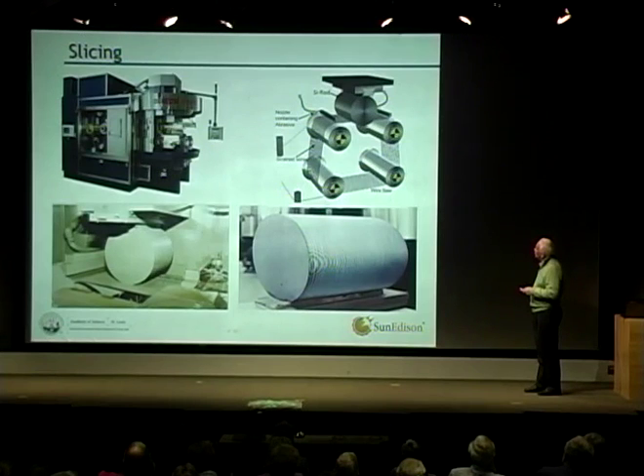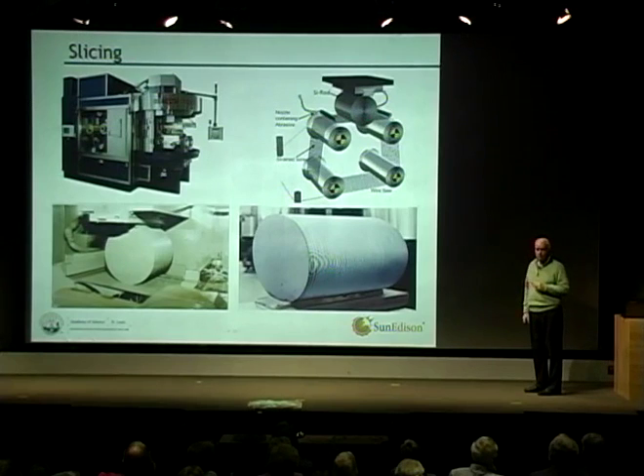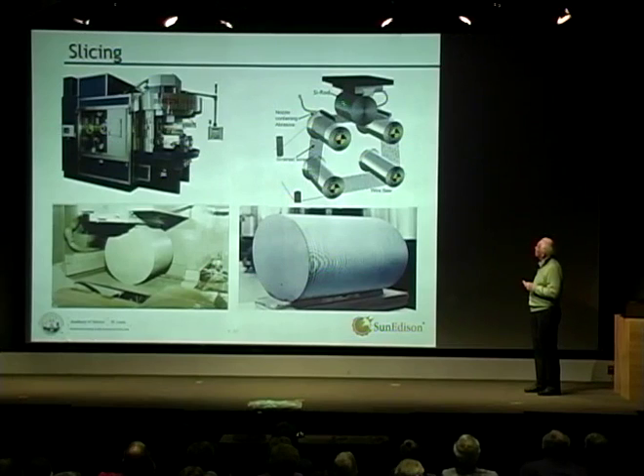What happens is, this wire goes in here across some rollers, across the top, down, and back across the top, and so on, like a kind of spiral helix. And then it goes back out here, taken up on another spool. So you have this whole series of wires, and we pass a slurry over the wires, containing silicon carbide or something like that. And then the ingot, or the silicon crystal, is mounted on a carbon beam, and we gradually lower it through these wires as the wires cut into the silicon.